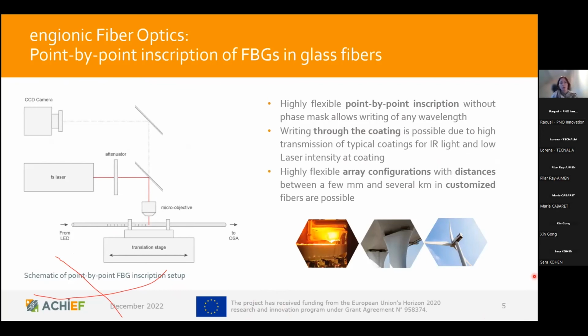These are commercially available optical fibers, and the advantage of our fabrication route is that we do not care so much about the coating material, as the infrared laser usually passes through the coating without any harm. So we can prepare very customized and well-defined fiber Bragg gratings.